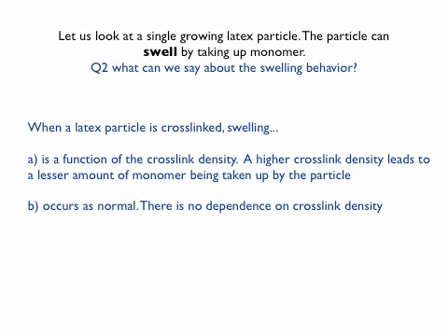Well, for example, if I would use divinyl benzene, I have two vinyl groups then, and basically I can attach polymer chains to each other. So in the end, I could end up with one molecule, one particle is one molecule, but obviously I can increase my cross-link density if I use more divinyl benzene in this particular case.